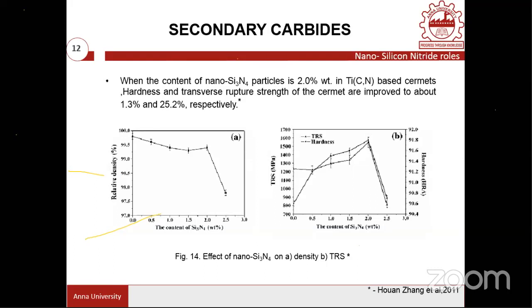And here the relative density is also affected by the addition of Si3N4. The relative density is basically maintained up to 1%, but there is a drastic reduction after 2%. So there would be some reduction due to this addition. Also, the nanoparticles will form agglomeration, and as a result it would affect the sintering. But when you add a nanoparticle, you should have a uniform distribution of this Si3N4 or any other nanoparticle in the powder compaction. Otherwise, the density would be a problem.